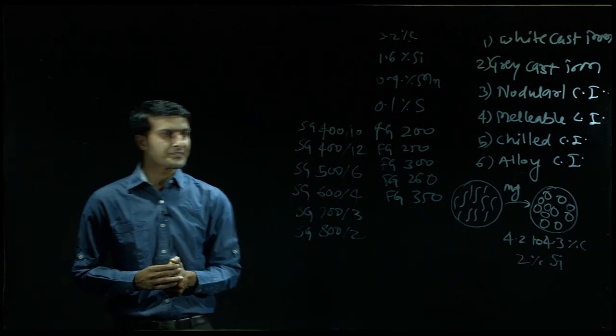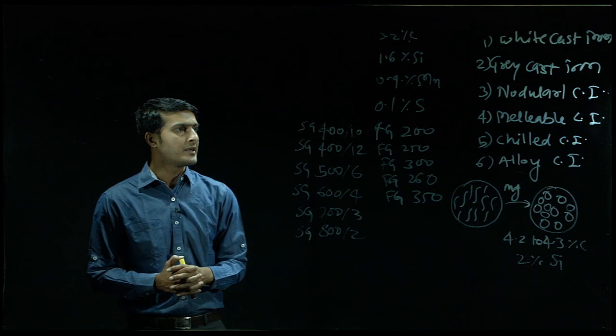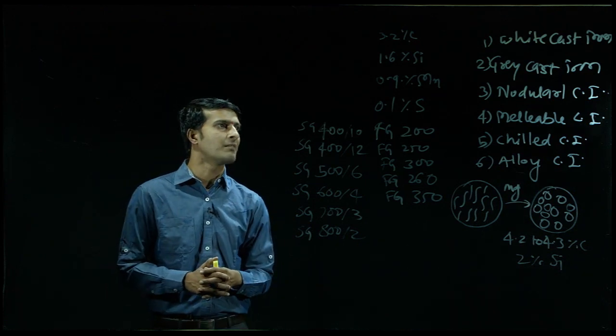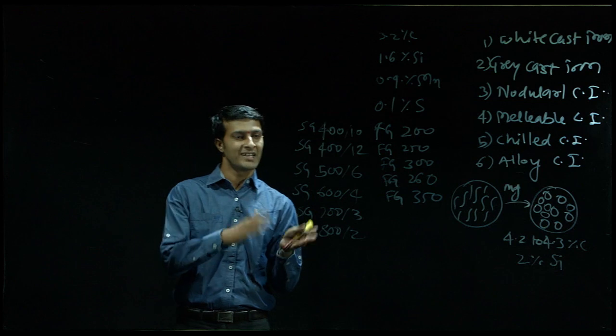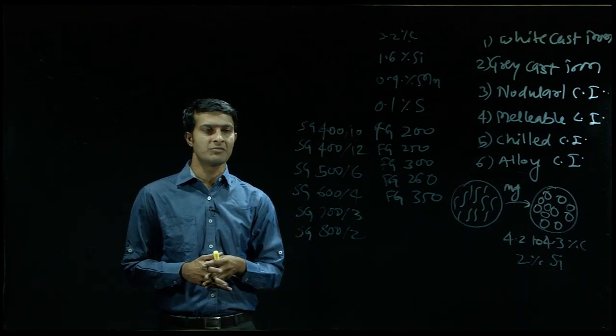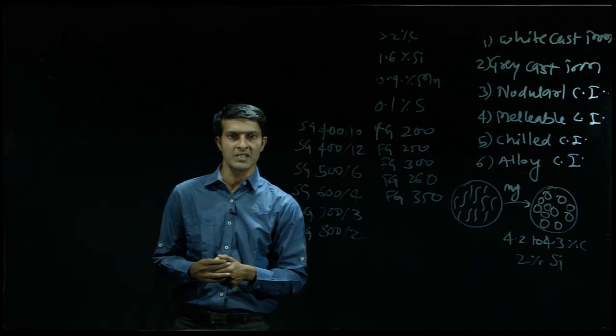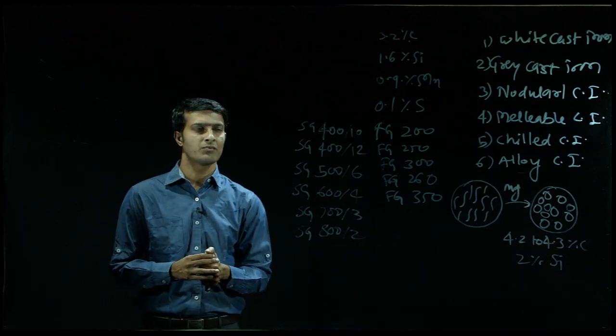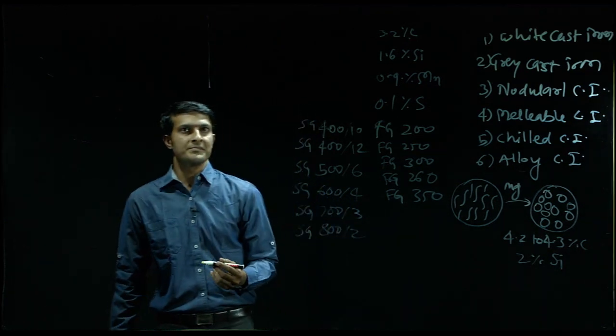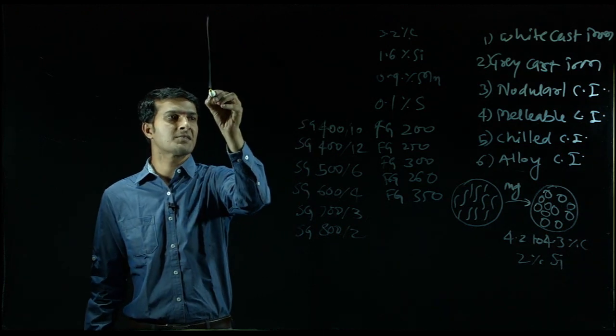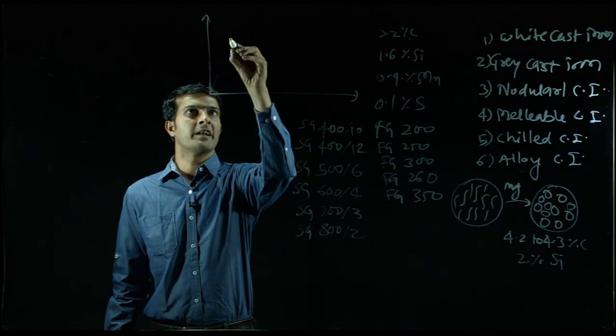The next one is malleable cast iron. Malleable cast irons are basically produced from white cast iron by using a heat treatment called malleablizing heat treatment. Since white cast iron's elongation is very less — less than 1 percent — malleable cast iron produced from it gives near about 6 to 20 percent elongation. This is produced by heating the white cast iron pieces in a furnace slowly up to 900 to 950 degrees Celsius.